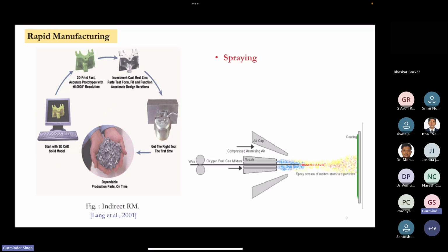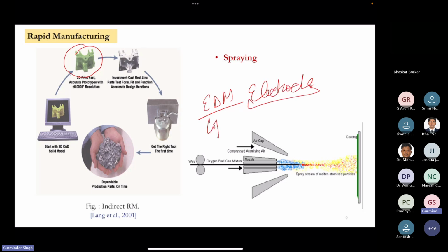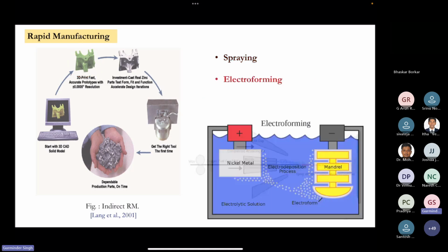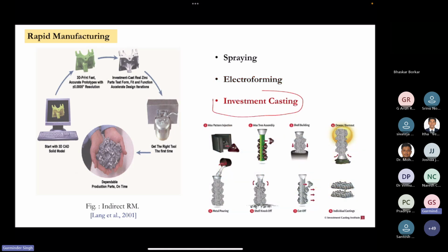issues. So there are some other alternatives: you can have a polymer 3D printed part, and you can use a spraying machine to spray metal on the polymer 3D printed part to make it conductive. This type of conductive part can be used for EDM electrodes, because it will have a coating of copper material, which will be conductive in nature, and it will give a full channel to discharge and charge to make a plasma channel for melting the workpiece for cutting. And similarly, electroforming. In electroforming, you can also deposit the electric material on the surface of the printed part to make it more conductive and metallic. Another is investment casting, of which I have already given one example.